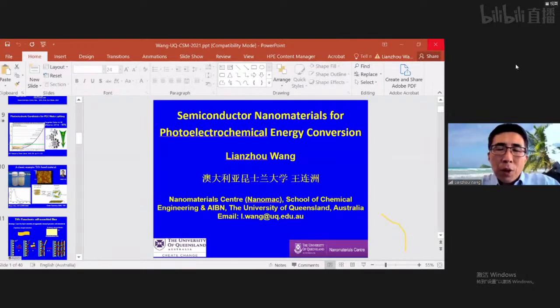But if we look at our PEC system, we also check the PEC performance over a period of time, like bismuth vanadate, the best performing one, and the performance is still pretty good in the long term. In other systems like the iron oxide system, it's pretty hard to stabilize. It's really dependent upon the material system, and some intrinsic properties of the photoelectrode materials can also affect the oxygen vacancy stability. Great, thank you.